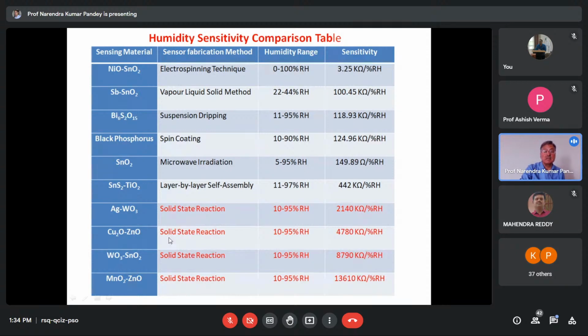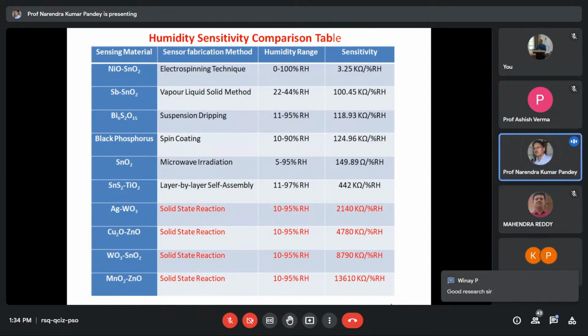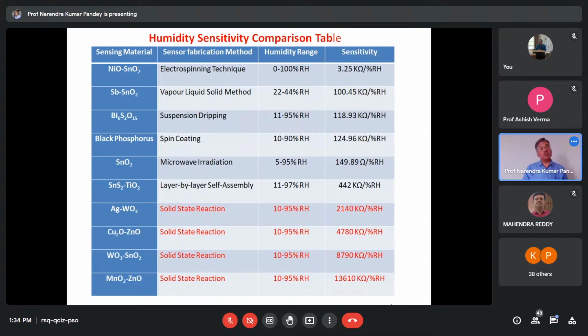Cu2O ZnO, that is in IEEE Sensors, again published here. There, this much is the kilo ohm per percentage sensitivity. For this one, we are getting this, and for MnO2 ZnO solid state reaction, we are getting this much sensitivity. So we are getting a very highly sensitive material for sensing application. The only thing is that we are trying to control the aging. We are trying to control the hysteresis. We are trying to improve upon the response recovery time, etc. So various parameters of the sensors have to be looked into for improvement through experimentation, through trial and error, and some optimization has to be done.